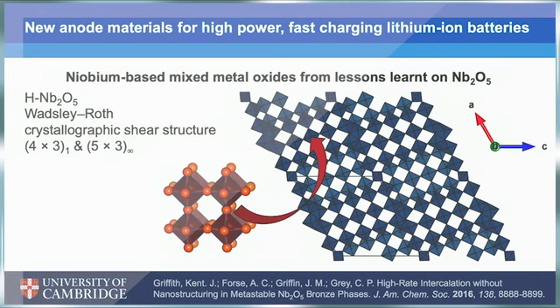And the crystal structure I'm showing is called a Wadsley-Roth structure or a crystallographic shear structure because it's made up of blocks that are ReO3-like. And so on this inset in red, we have the ReO3 structure, which is perovskite without the A-site cation. And this ReO3 structure is perfectly corner sharing. But in Nb2O5, we don't have that 1:3 metal to oxygen ratio required for perfect corner sharing.